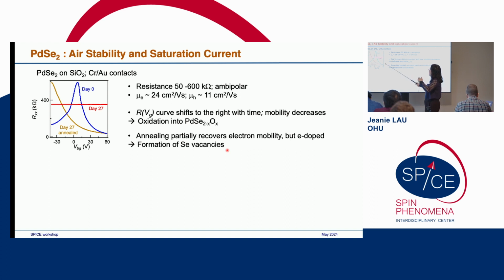But remember this was actually claimed to be air stable. If we leave it outside, it turns out the curves just shift and the mobility will decrease. By day 27, there's really no gate response, and the resistance when it's highly doped becomes much worse. So it is not completely air stable.